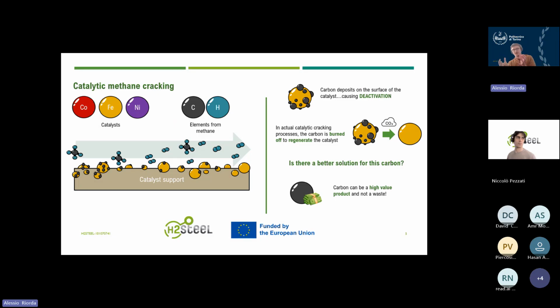Because when it's covered with solid carbon, it is not working anymore as a catalyst. This is not something new. The petrochemical industry has known that for a lot of years. Indeed, normally in the catalytic processes, like for the production of more gasoline from a higher molecule of hydrocarbons, they normally burn off the carbon. So they take the catalyst, they burn off the carbon, and then it's regenerated and it can work again. In this case, we don't want to do that, because the carbon that we are depositing on the catalyst can have a high value, and we can just use it and commercialize it. That's the point of the technology of the methane cracking.